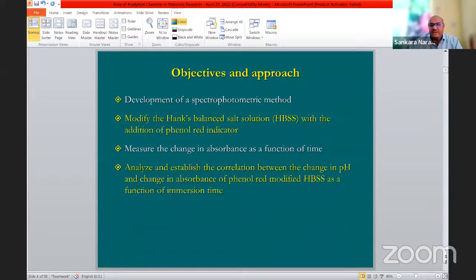So to avoid that, we want to develop a spectrophotometric method. The idea is to develop a simple method. We used the Hanks solution as the simulated body fluid and added phenol red as an indicator, because we want to follow the corrosion of magnesium by a spectrophotometric method. We took samples as a function of time and measured the change in absorbance of the solution. Because it's a colored solution, we can monitor its color absorbance.